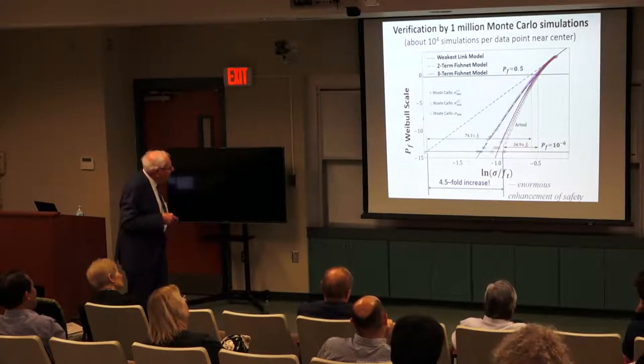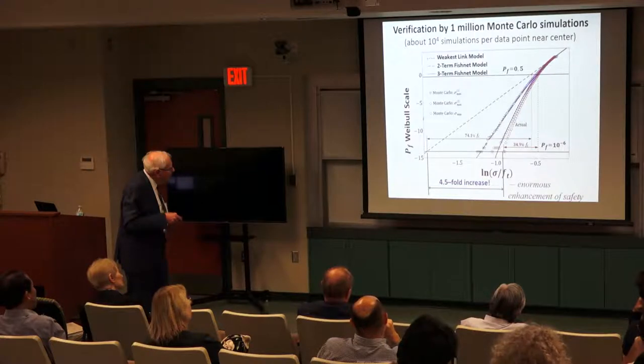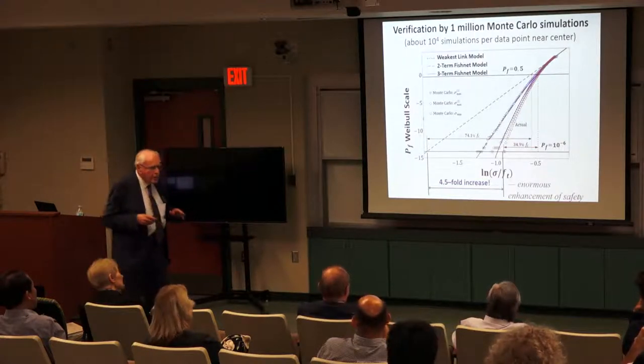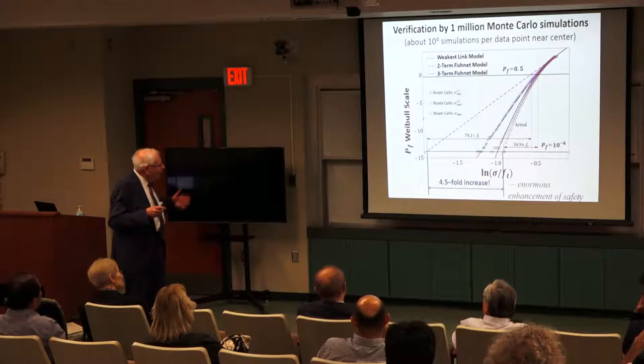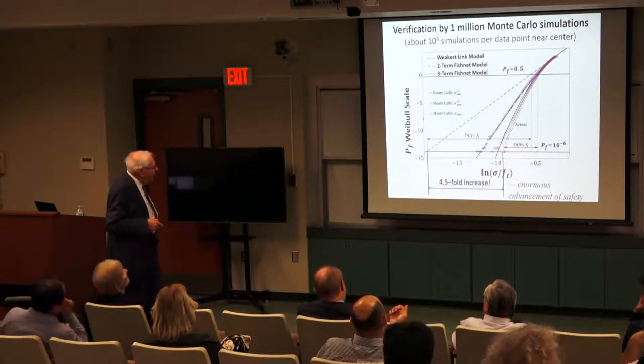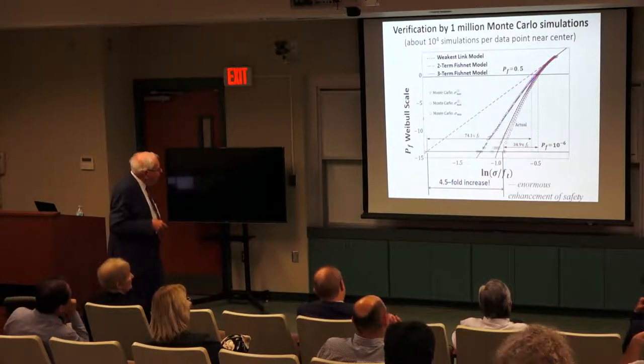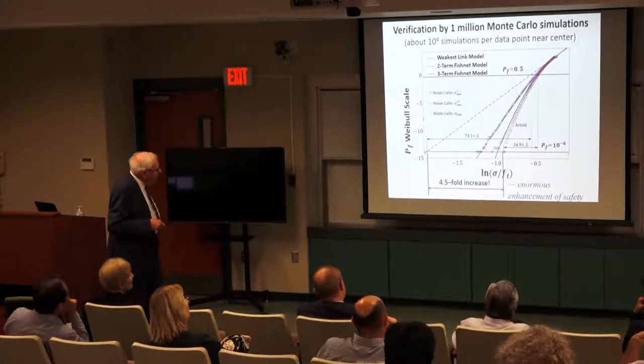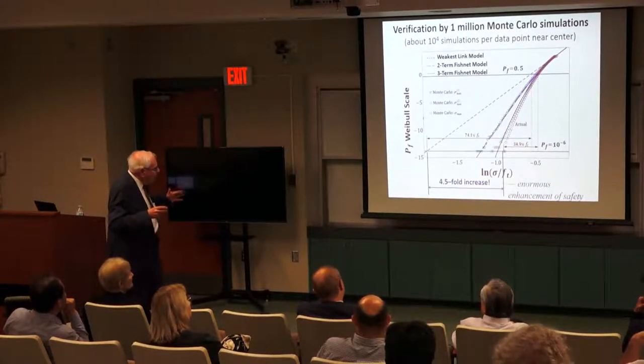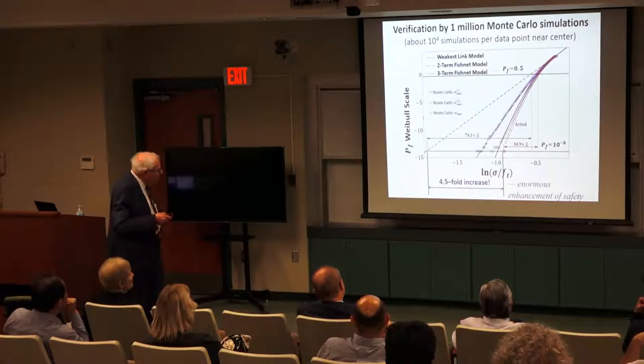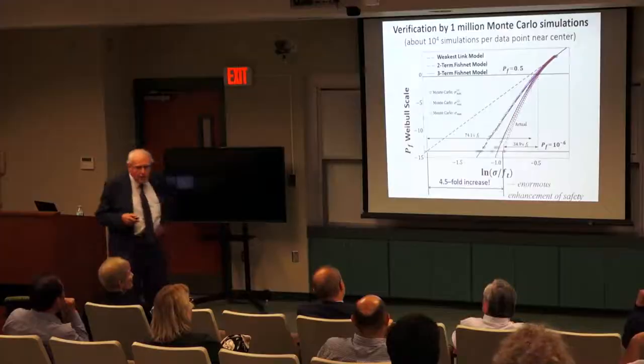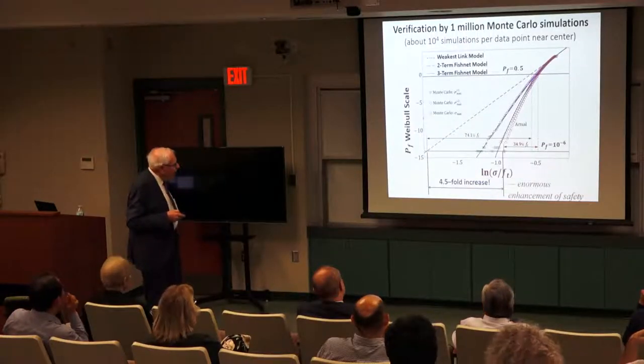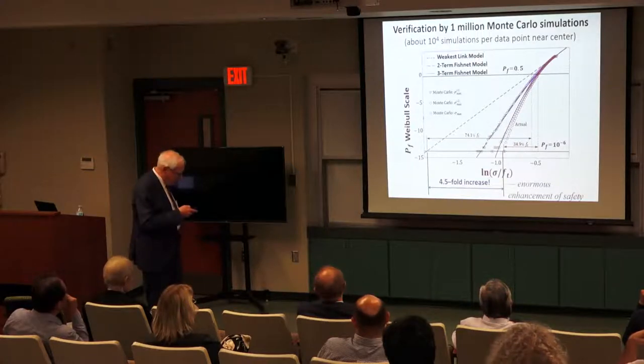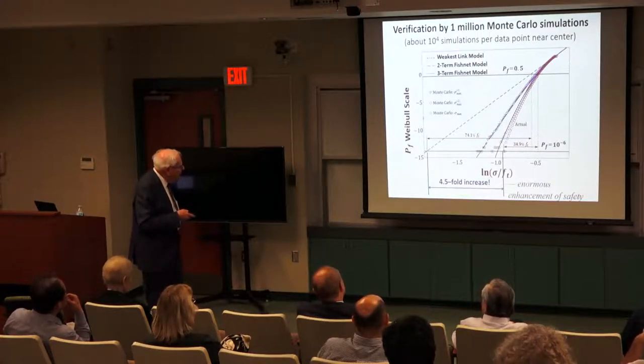So this is the analytic two-term fishnet. This is simulation. It means we exclude all failures where more than two links failed. Then this is the three-term fishnet. It matches very well. If you let any number of failures occur before overall failure, you get this line. You see how close it is? For most practical purposes, it's good enough. So we cannot get actually analytical solution exactly for any number of them, but we get close enough analytically and in a simple way.